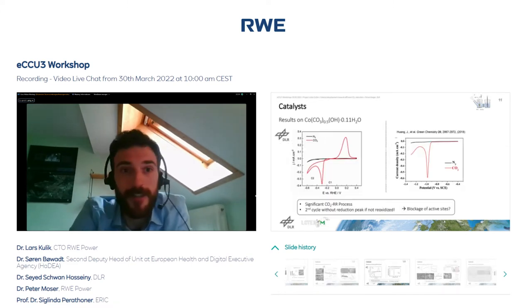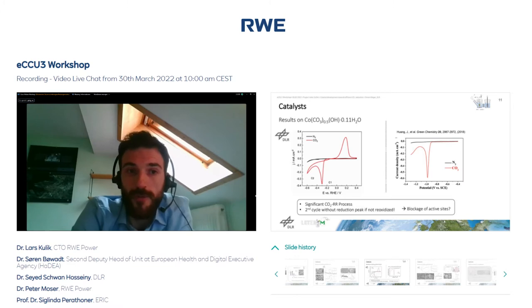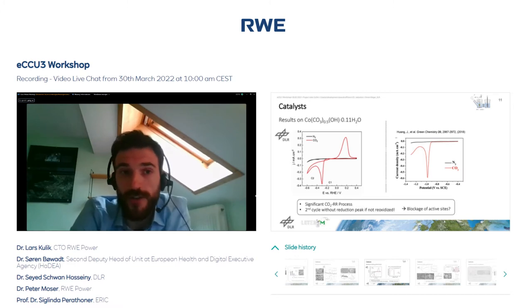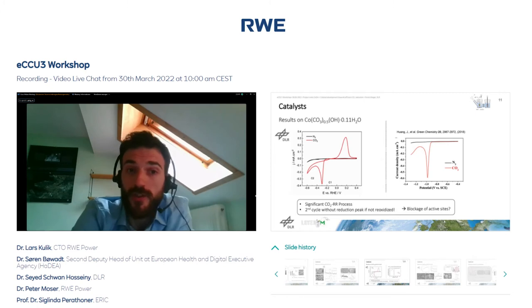Going to slide 11, there's the comparison of the electrochemical characterization. Here you can see a cyclic voltammogram. Basically, you sweep the potential from a lower potential to a higher potential and back, and then you record the current, which is shown here. With black, there is no real process noticeable because only nitrogen is used, and in case CO2 is used, one can see here in red significant reduction progress in both cases. The only difference, and maybe an important difference, is that this was an irreversible process in our case. So this was only happening once, and in the second sweep there was no reductive process anymore, which leads us to the assumption that there is some blockage of active sites.